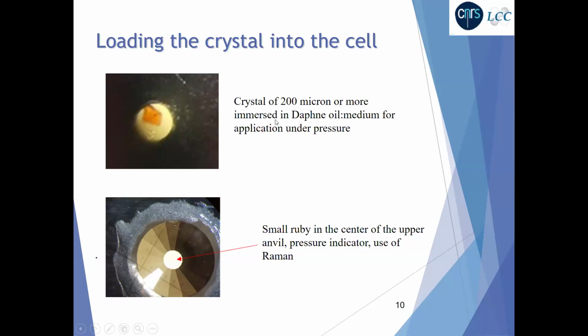The crystal is immersed in a Daphne oil in our case. This is a medium for the application of the pressure. The maximum pressure will depend on the medium. In the case of our studies for the moment, the maximum pressure we want to reach is a few gigapascal, and so the Daphne oil is a good medium for that. Then we put a small ruby in the center of the upper anvil, and the ruby is used as a pressure indicator that we will check by Raman spectroscopy.